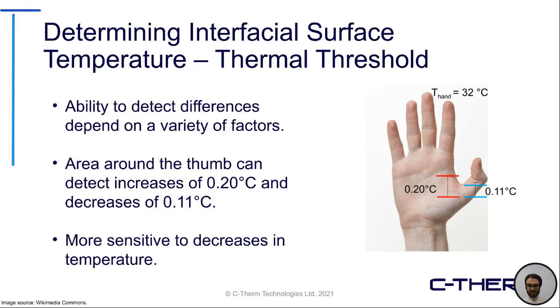So there are a lot of things to consider here, but if we use a generic baseline of the human hand, it has been shown that the area around the thumb can detect increases of temperature as low as about 0.2 degrees Celsius, and decreases of down as low as 0.11 degrees Celsius. So this can give you a rough idea as to what types of differences can be detected, and therefore which ones would be significant when you're comparing different materials.